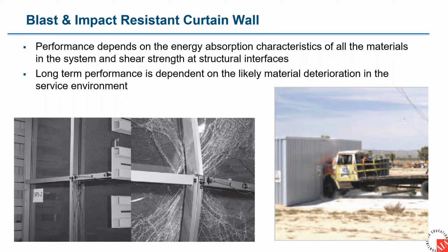Additionally, it's important to note with that stainless steel curtain wall, if your outer panel is stainless steel but you've used something with less ability to absorb energy, like aluminum or carbon steel behind it, then your whole system is limited by that structural material. So if you need the maximum impact resistance, blast resistance, or fire resistance, the whole system has to be stainless steel.